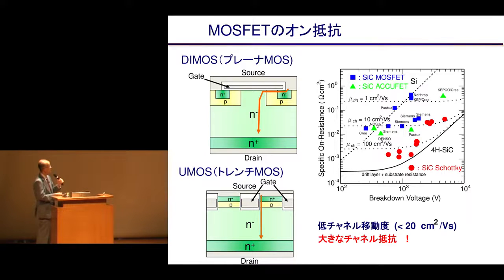So there's breakdown voltage on the horizontal axis and specific on-resistance on the vertical axis, which shows the loss. With increased voltage, a unipolar device has high resistance. That's the limit for the silicon. In the case of silicon carbide, as I said, there's about 2.5 times.